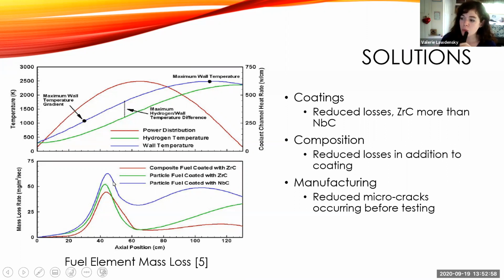So what they ended up doing is finding that if they increased the carbon content in the fuel elements and made sure that they had a coating that had a closer coefficient of thermal expansion, and then ultimately included zirconium carbide in the fuel elements matrix, they were able to more closely match those coefficients of thermal expansion, and the cracks were drastically reduced. You still had a fair bit at that peak region there, but it was enough that you knew you were in the right direction.